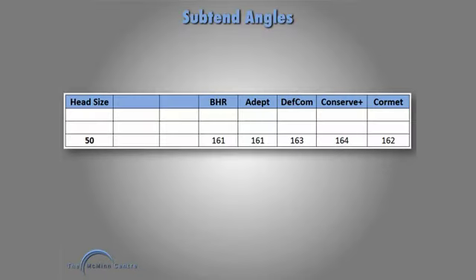Now, there's the subtend angles in a range of different resurfacing devices with a 50mm head. They're all 160 something degrees. And by way of stark contrast, the ASR at a 50 head size has a subtend angle on the acetabular articular surface of 148 degrees, and we know that the ASR failed by edge loading and edge wear. There were a number of other failure mechanisms, but that is number one culprit.